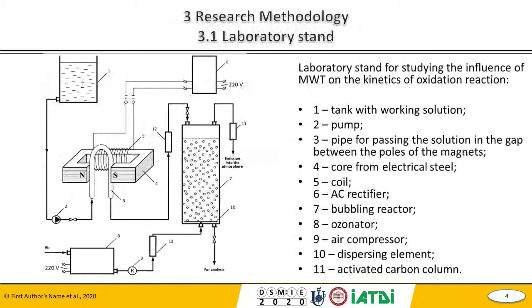Please, next slide. For the experimental studies, a laboratory stand was made. The working solution of oxalic acid is pretreated in the magnetic field. As a result, there are physical-chemical changes in the solution, which affect the kinetics of further reactions. After the magnetic pretreatment, the solution is fed into the bubble column for the common process of ozonation. A series of experiments were carried out according to a similar process scheme. The effect of each of the defined mode parameters was studied independently.